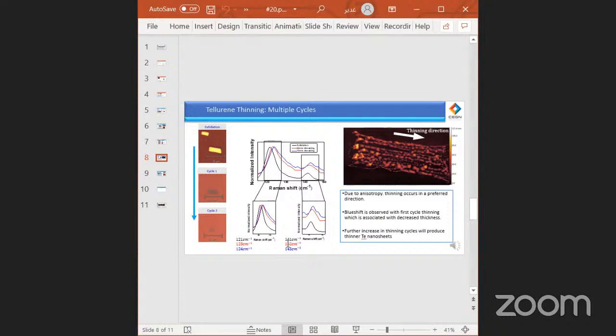During the Te thinning, the etching prefers a specific direction, where it's most likely due to Te anisotropy. And we're positive that it's not related to the gas flow direction, where we have multiple samples that prove this indication. Also, a further increase in thinning cycles will produce thinner Te nanosheets.